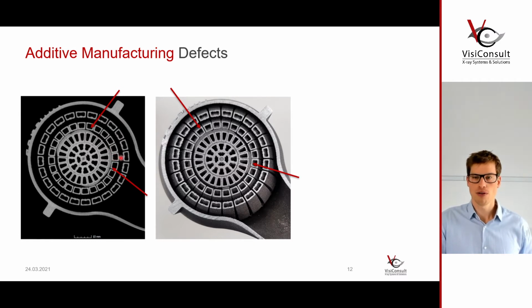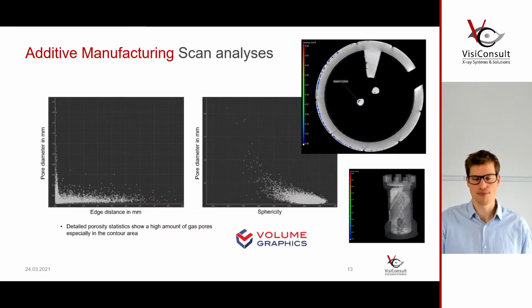This becomes even more important if you apply a process called hipping, so hot isostatic pressing, so applying heat and pressure to harden the part and to fuse out some of the porosities inside. But if you at that point have residual powder left in the part, it's of course fused to the part and stuck there and will never come out. So you probably want to find out before you heat treat the part if there's residual powder, and you would want to try to get it out before you fuse it irreversibly into the part. That's a major important analysis.